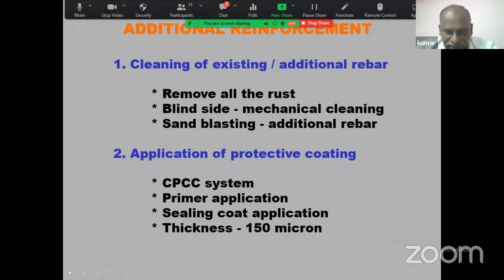When the crack is sealed, then after that, we can go for the additional reinforcement. The existing reinforcement, we have to clean properly, and you have to add the additional reinforcement. For both reinforcements, remove all the rust. The rust product on the surface is to be removed properly. The blind side of the reinforcement, on the other side, is to be cleaned by mechanical cleaning. Sandblasting you can use on the additional reinforcement to remove all the rust. This is the cleaning method you can use for the existing as well as the new reinforcement.